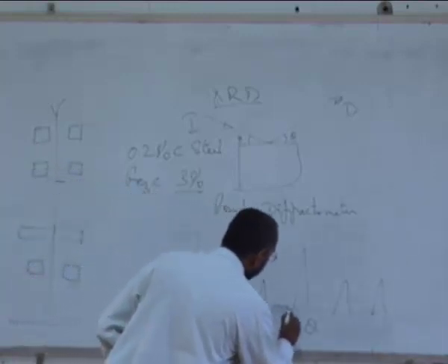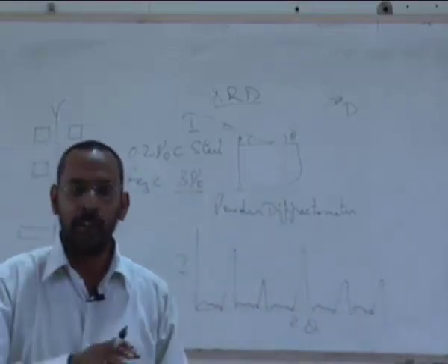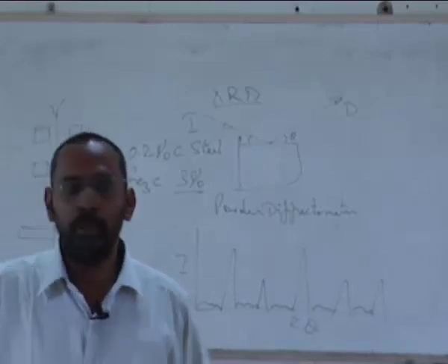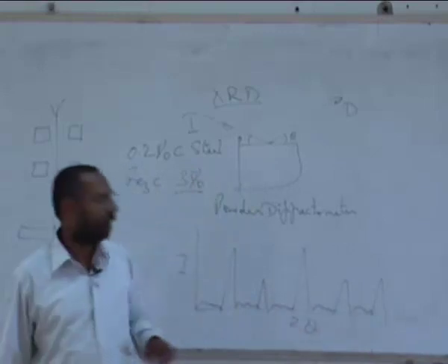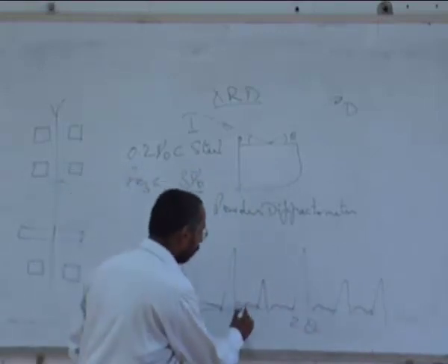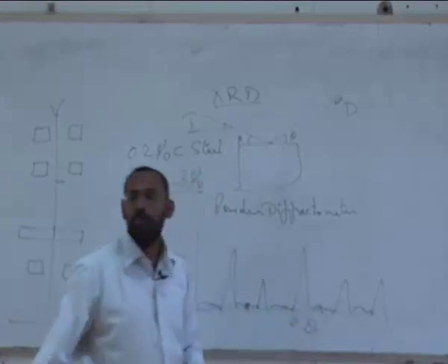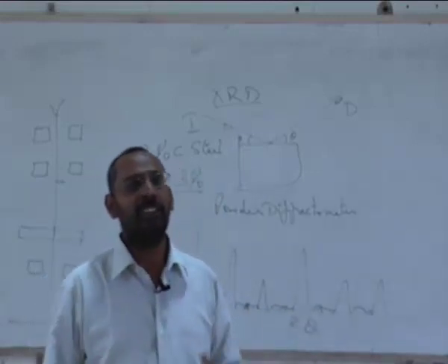There is always some background noise because of the roughness of the sample. There is always some random scattering. However nicely you polish your sample, you will have some roughness which is also causing some kind of noise. And so these peaks are so small, and they may get merged into this noise. And as a result, you may not be able to see the Fe3C very clearly.